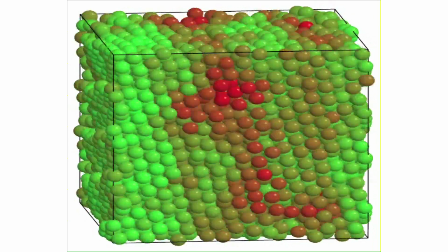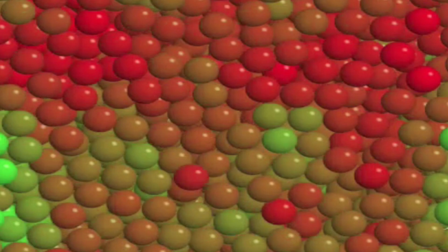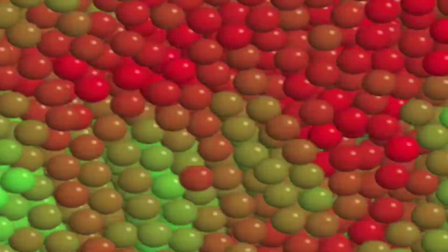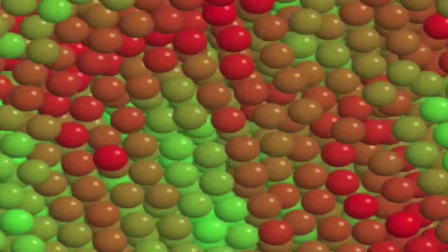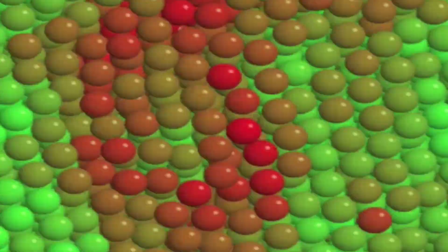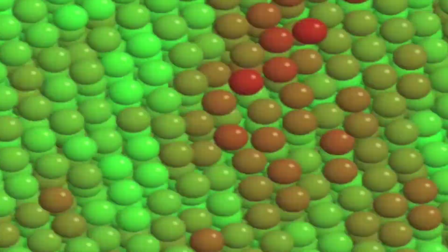I've got a bigger question than that. What's the difference between an ordered sphere and a non-ordered sphere? They were just a bunch of spheres in a box. No, but it's the relationship of the spheres with each other, the positions of the spheres with each other. So you can look at something called a correlation function, and you can see how one sphere is related to its neighbours, and you can use that to work out the degree of order. It's something called an order parameter. So that thing kind of ordered itself, like a beehive. Exactly. That's it. It ordered itself just due to entropy. So this is why this idea of associating entropy with disorder is really misleading from a number of perspectives.